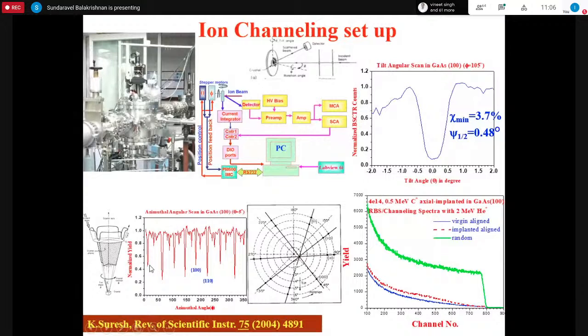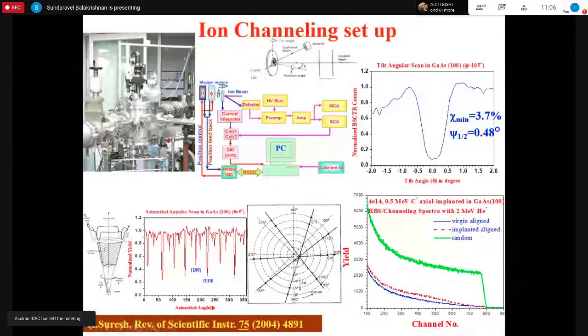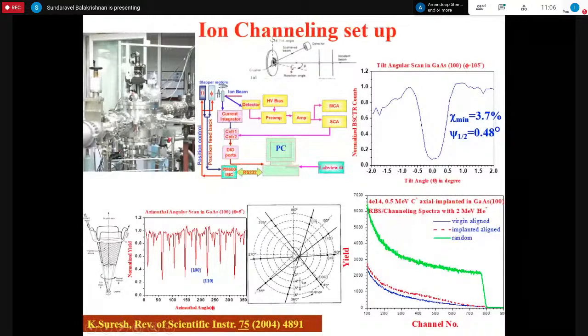So we take a polar plot. In the polar plot, whatever is the point at the center, that is the normal axis. There, phi is also 0. Then you tilt the sample by 1 degree, and at 1 degree tilt angle, we make that axis precess about this center. Then you get a cone, and the projection of the cone is a circle. So the value of this circular position tells about the angle theta value.